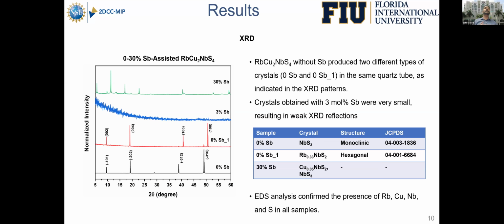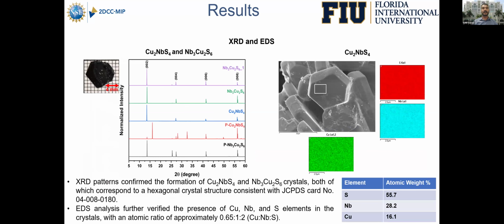While optimizing the growth of these materials, we came up with very exciting hexagonal shaped crystals without Rb, which is copper niobium sulfide. As you can see in the picture, we have a very big and beautiful hexagonal shaped crystal structure, and through the SEM images, you can see the hexagonal shaped geometry.